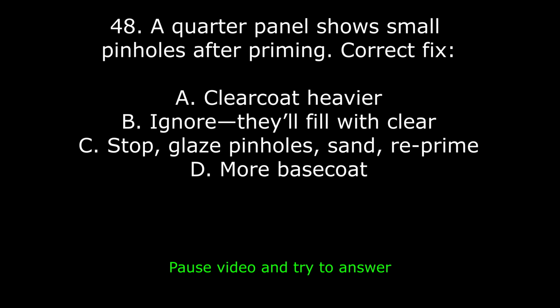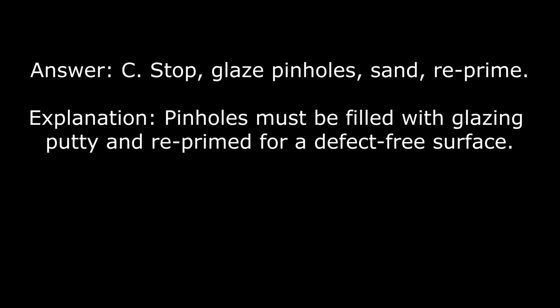48. A quarter panel shows small pinholes after priming. Correct fix. A. Clear coat heavier. B. Ignore, they'll fill with clear. C. Stop, glaze pinholes, sand, and reprime. D. More base coat. Answer: C. Stop, glaze pinholes, sand, and reprime. Explanation: pinholes must be filled with glazing putty and reprimed for a defect-free surface.